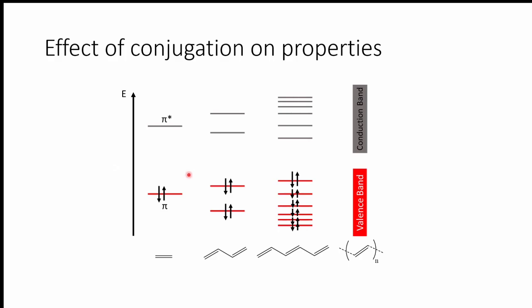So if we look at something that is just a single double bond, you have the highest orbital being a pi and then an anti-orbital being a pi star. And as you start adding double bonds, you start getting this conjugated effect from the even odd type of thing where you have double bond, single bond, double bond. And then what that leads to happening is that you start getting the gap between the highest occupied orbital, which is this one, and the lowest unoccupied orbital to start to get narrower and narrower. And if you go to an oligomer, you're getting more conjugation. And then at the end of the day,